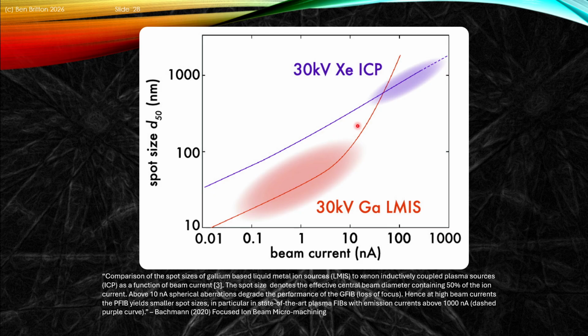The xenon FIB typically has a larger spot size. It's up at the sort of 10 to hundreds of nanometers, depending on how we set up the instrument. It can be made a bit smaller if we want to optimize it. But here we can effectively use xenon, and we'll see this a bit later, but xenon is a large and heavy noble gas, and so it's very effective at sputtering. Gallium is much lighter, and it can form alloys or amalgams with certain systems, and so that's one of the reasons why you might use the two different source types here.